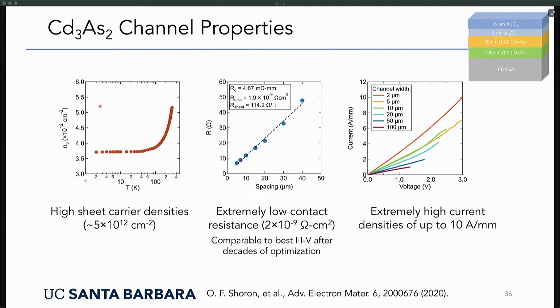At room temperature, for example, we can get charge densities around 5 times 10 to the 12. This is quite good. What is especially good are the extremely low contact resistances. In this particular device, it's actually better than most III-V contact resistances. What is also very attractive are the extremely high current densities. In narrow channel devices, we could get current densities up to 10 amps per millimeter, which is very, very high. The reason is the relatively high charge density, but also the high velocity in this material.